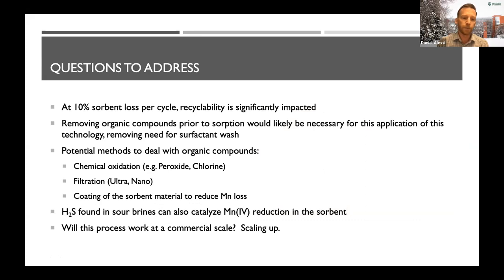So one easy solution here would be to pre-treat the brines. And this has been talked about a lot. What you could do is some sort of process before the brine even sees the lithium DLE material, to remove the organics, or at least knock them down to much lower concentrations. And of course, that's going to limit the physical coating of the sorbent that we talked about, but presumably it's also going to reduce the reductive dissolution, right? The reduction of manganese 4 to manganese 2, and then its loss in the acid step.